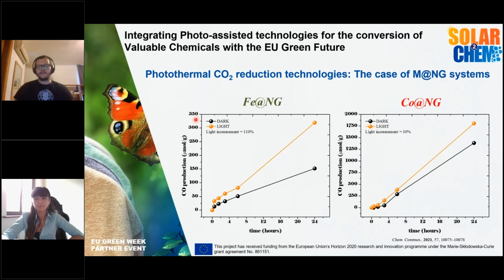So the next part was just to figure out what was giving the light enhancement. So we considered two different systems. One with the isolated iron clusters on nitrogen graphene, and one with cobalt. And we could observe that indeed in iron, despite the activity being a lot lower, something that is already well known in the literature, as iron is not as good in regular hydrogenations as cobalt, the light enhancement was more than double.